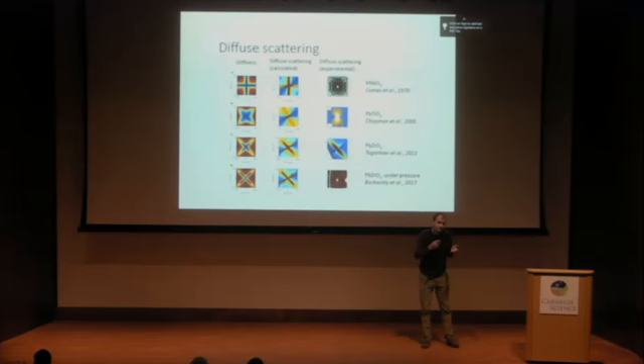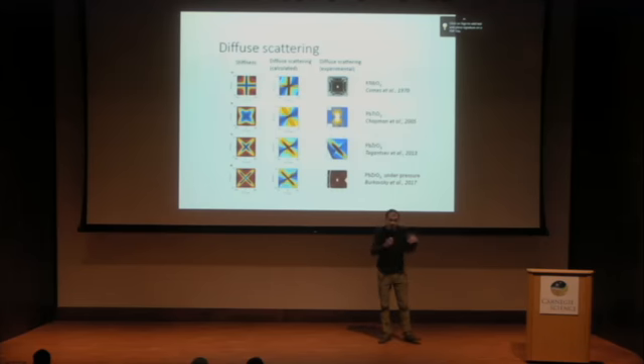On the top you see showing diffuse scattering patterns of sodium niobate. It is roughly the same as calculation gives. When the polarizability of oxygen is nearly isotropic, the second row, there is no special anisotropy also in the stiffness landscape. And this is something that we see in lead titanate, as Chapman et al. report. With lead zirconate, there is strong anisotropy. It looks like butterflies, and it is similar to what we see in relaxors. And it is consistent with the experiments of Tagantsov and co-authors.